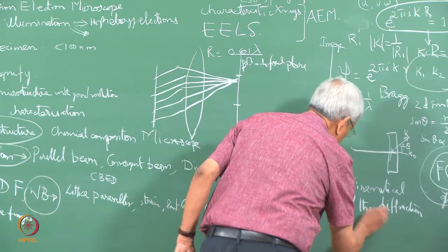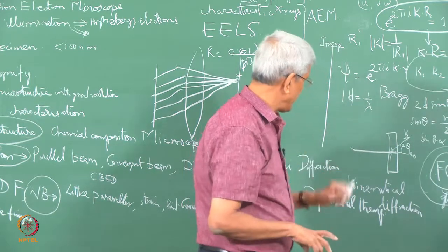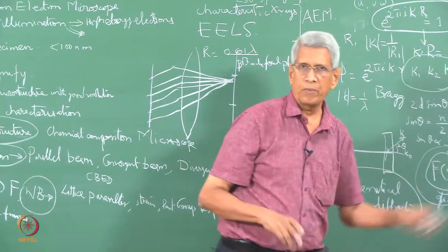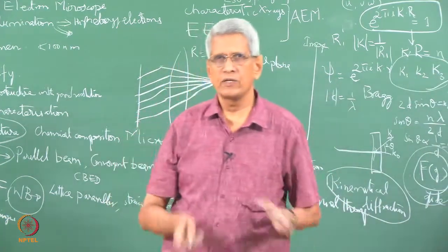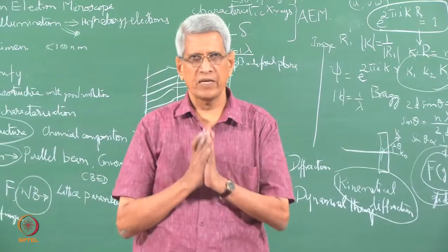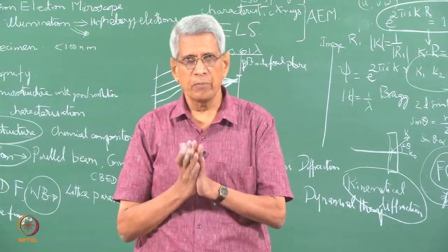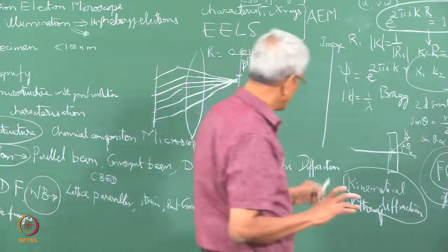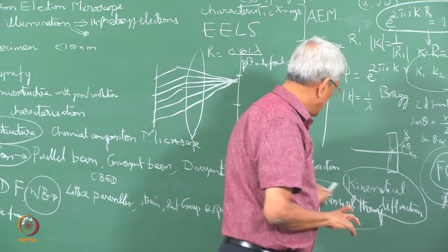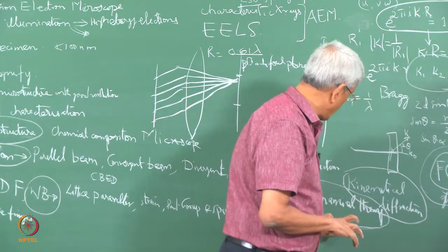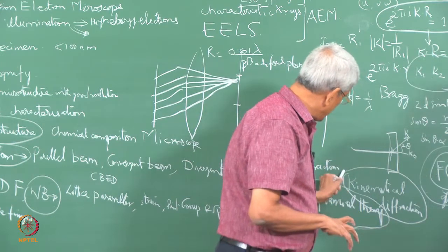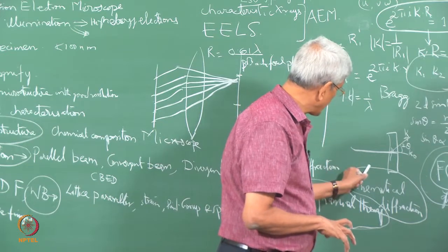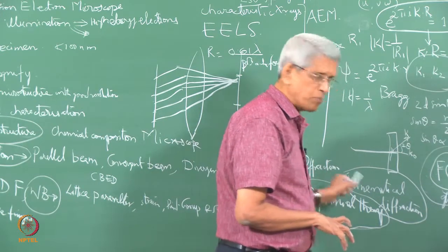Okay. So, what we can understand is that in the case of X-rays, kinematical theory could be used to get information about the crystal structure. With conventional parallel beam electron diffraction patterns, if you wanted to determine the point group and the space group symmetry, it is not possible, because the dynamical theory is the only one which has to be applied, and because various types of diffraction like double diffraction take place, the spots which kinematical theory does not allow could be present.